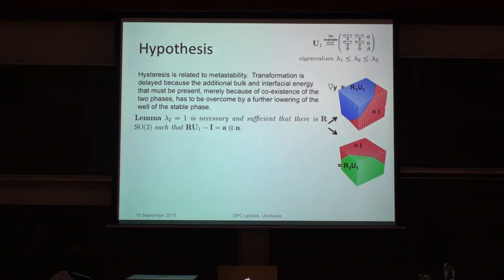So this is the austenite. This underwent the distortion. It's also been rotated a little bit. But you can rotate it a little bit such that it fits perfectly on the austenite. So you don't need the twin. You don't need the second variant. You don't need the transition layer. You don't need the interfacial energy. So all that barrier is now gone if lambda 2 is 1. Okay. Now, so how do you make lambda 2 1?